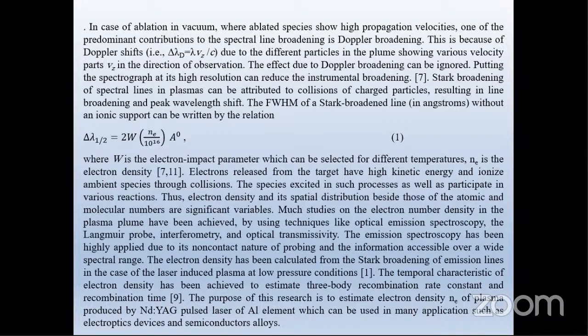Stark broadening of spectral line in plasmas can be attributed to collisions of charged particles, resulting in line broadening and peak wavelength shift. The full width at half maximum of a Stark broadening line in angstroms without an ionic support can be written by relation 1. This relation: delta lambda sub 1/2 equal to 2W NE over 10 to the power 16, in unit of angstrom. This equation describes the full width at half maximum of a Stark broadened line as mentioned before, where W is the electron impact parameter which can be selected for different temperatures, and NE is the electron density.